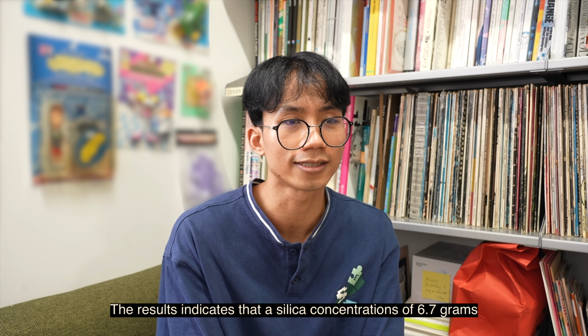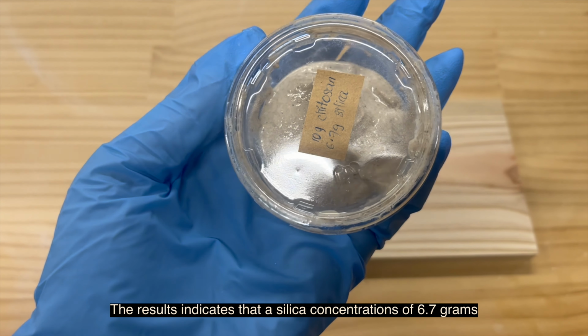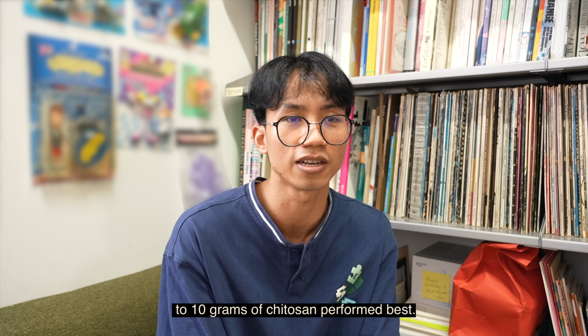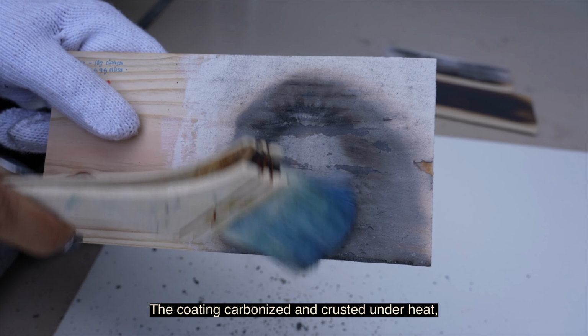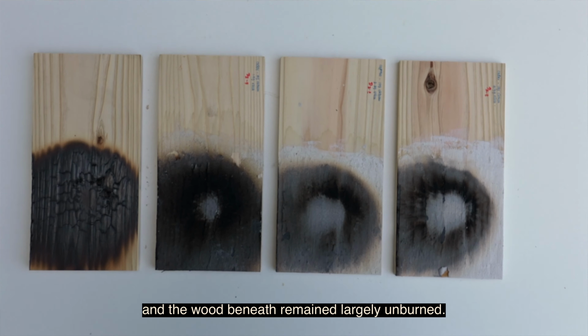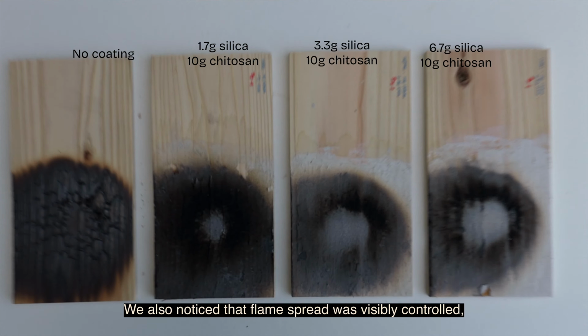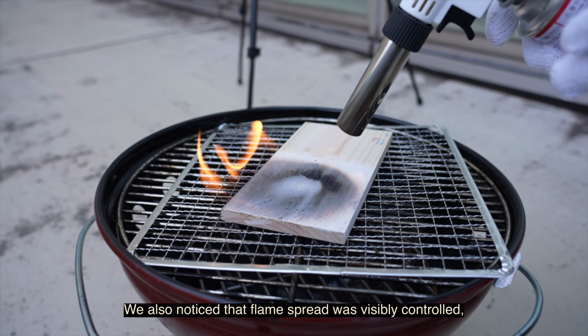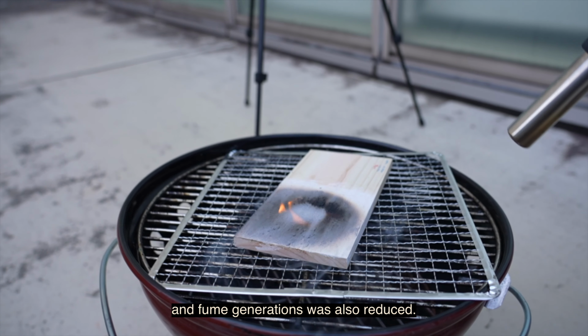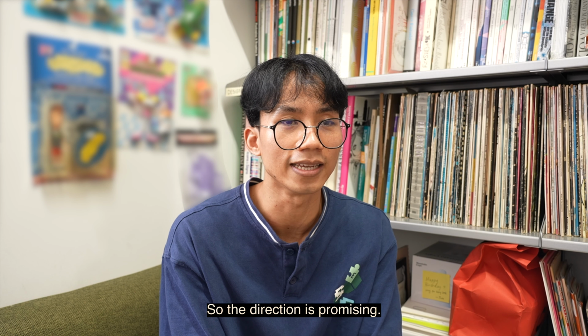The results indicate that a silica concentration of 6.7 grams to 10 grams of chitosan performed best. The coating carbonized and crusted under heat, and the wood beneath remained largely unburned. We also noticed that flame spread was visibly controlled and fume generation was also reduced. So the direction is promising.